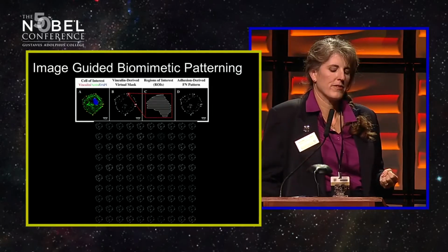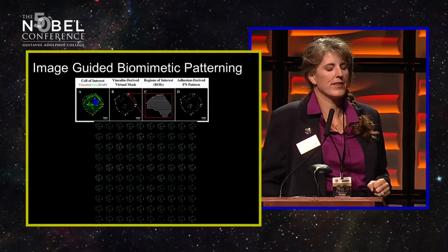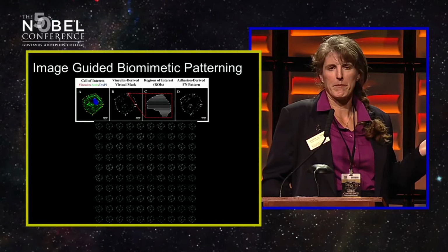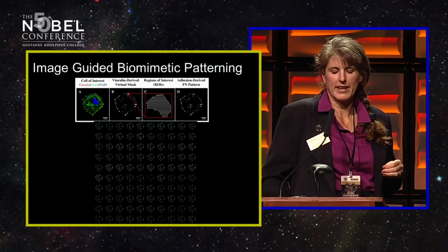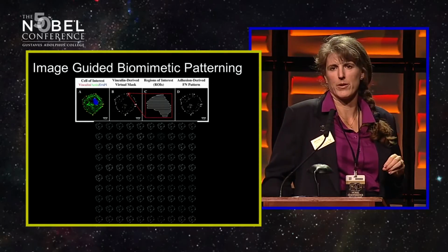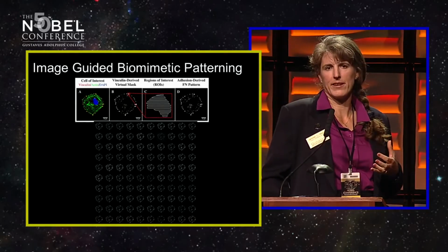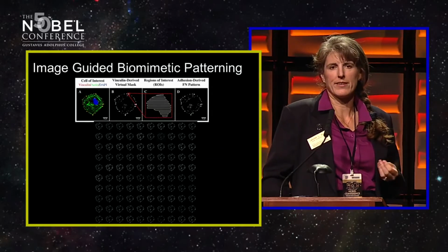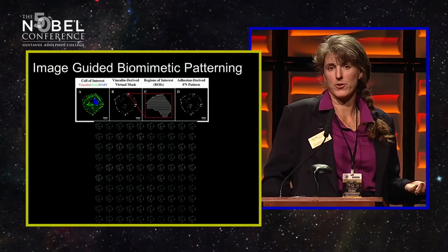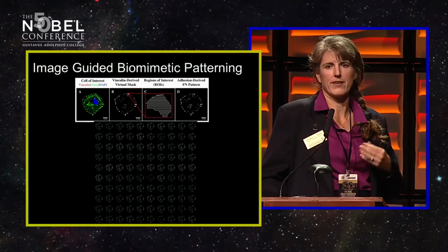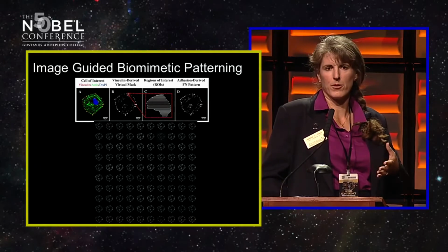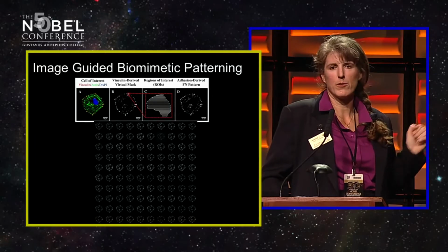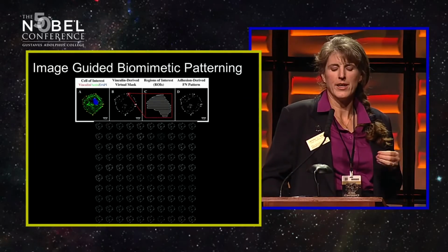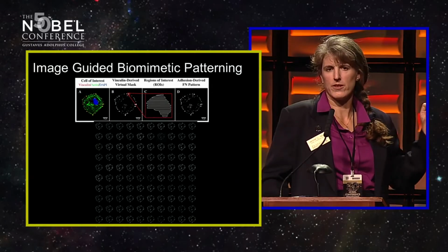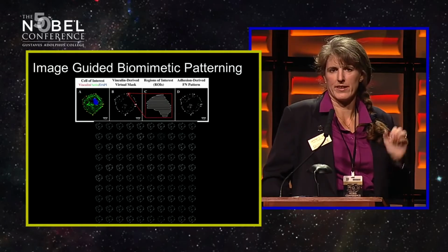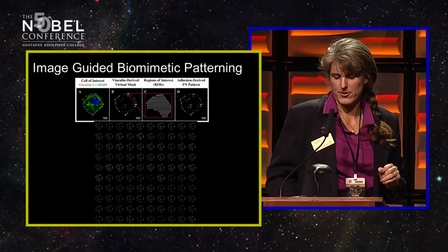And so one of the things we've done with this is to make very large arrays. At the bottom of this slide, you see an array of many, many cells that now look essentially all identical to each other because of the pattern they're growing on. The benefit there is that we have cells that are much more uniform in the way they're getting their signals and thus the way they should respond. So if we want to be screening new drugs or understanding the role of a cytoskeletal protein in a certain response, here we can start with a much more homogeneous population. We can change the pattern so that we change the cell phenotype, look at a different array of cells, and again get a much more homogeneous response and start to understand that.